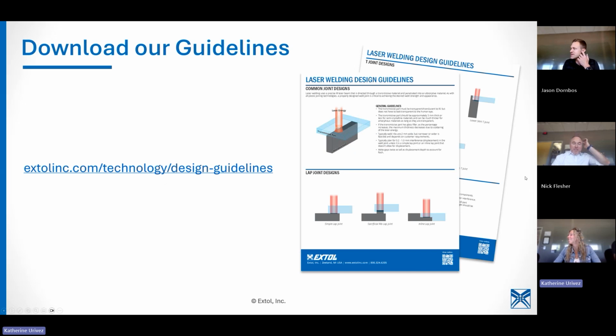I was just about to say, that speaks to what Gary had asked about earlier: how do you know if it's ultrasonic or if it's laser? It's typically cleanliness. That's probably the most common thing we see. Ultrasonic does a pretty good job, but there are times when you can't chance any dust whatsoever. So cleanliness is probably the biggest thing that we see. Precision is probably next. That energy goes nowhere else except where you want it to go. If you've done ultrasonic welding before, it can kind of run away from you in certain applications. And so those are the two biggest indicators.